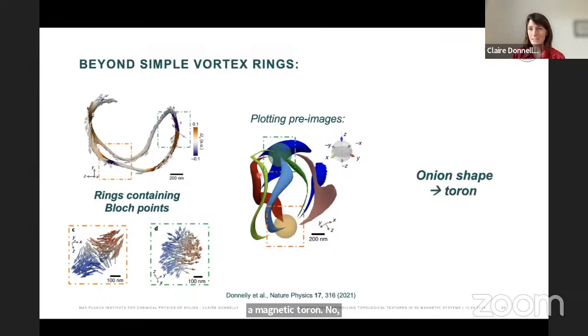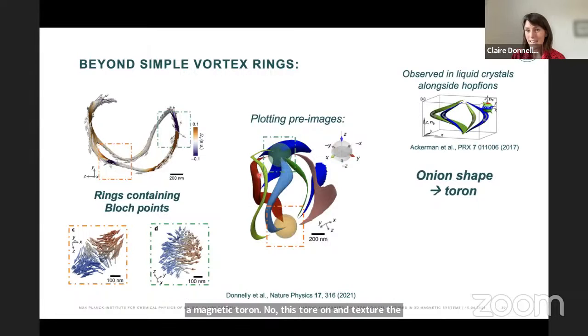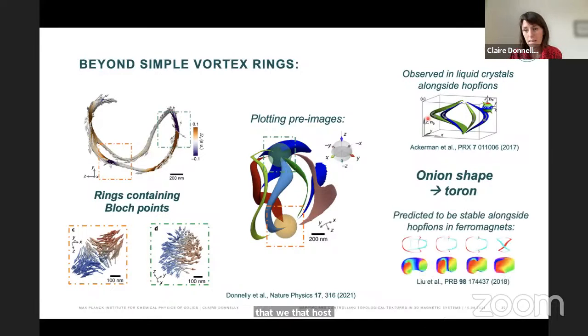Now, the reason why I say this toron texture looks familiar is that if we have a look at work from the field of liquid crystals, for example, they have also observed toron-like textures in liquid crystals. And what's quite interesting is that they observe them alongside these Hopfion textures. So it gives us some hope that systems that host torons should also be able to host these Hopfion configurations. In addition, micromagnetic simulations have predicted that these torons and Hopfions can be stabilized in the same system, and also that they can transform dynamically one into the other.